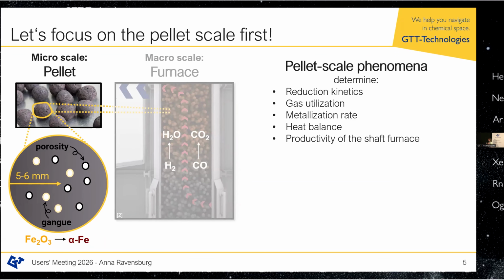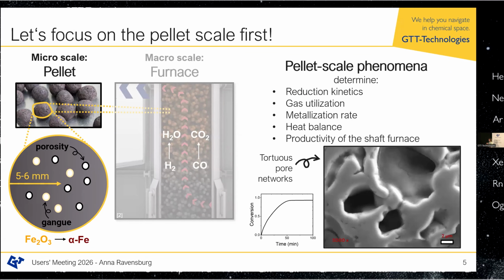And on the pellet scale, it's not only just one sphere and you're trying to reduce it. It's quite complex, the pellet itself is already quite complex in its structure. So you have this conversion curve, that is the bottom left plot, where you have the reduction of Fe2O3 with mass loss then to Fe. So a conversion curve value of 0 would correspond to 0 conversion, so Fe2O3, and then you have a value of 1 if you have converted it fully to iron, so a metallization degree of 100%.